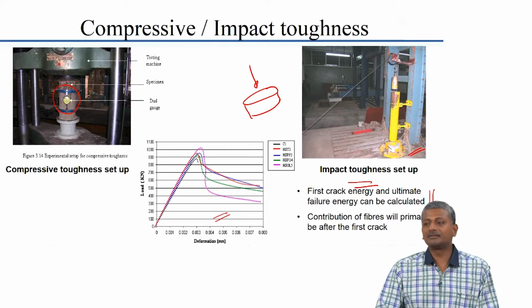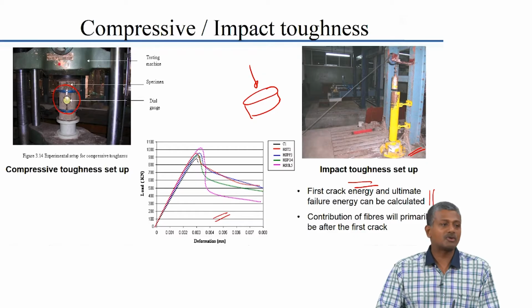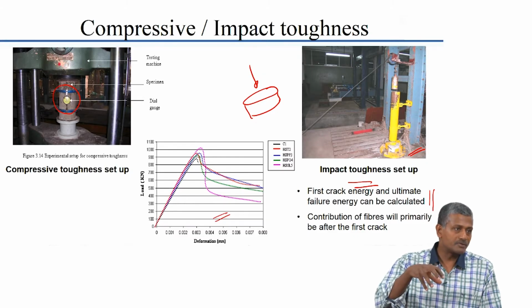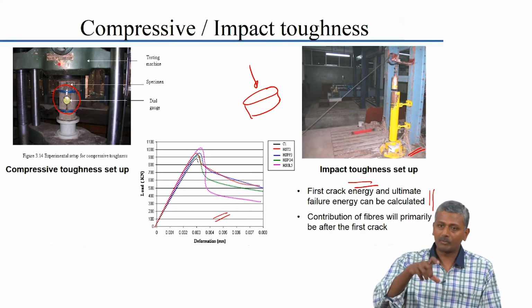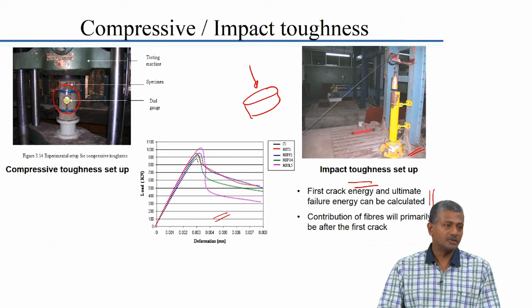As far as impact is concerned, we were looking at the number of times the load of a certain level was dropped from a given height onto the specimen, and the number of times that had to be dropped before the first crack appeared, and beyond the first crack the number of additional times that the load had to be dropped for completely splitting apart the concrete specimen. So, that was the impact toughness setup.